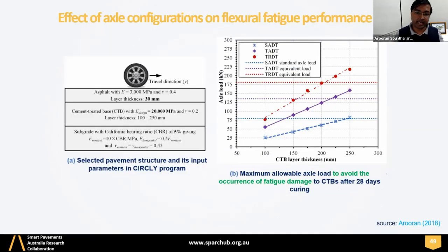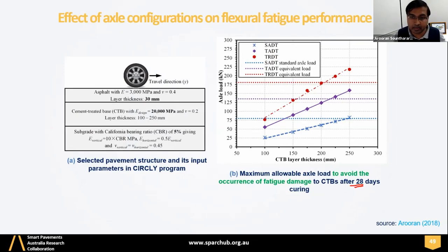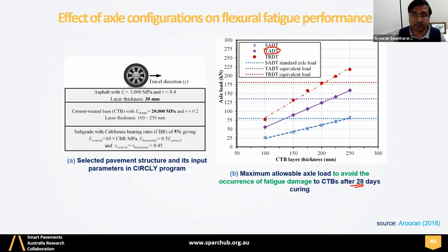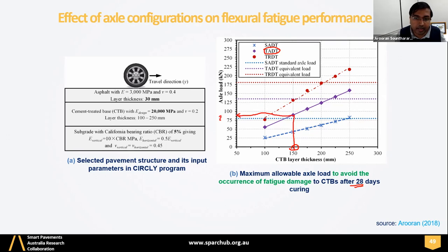Then using the fatigue curves here, we have identified the maximum loads that can be applied on this pavement after 28-day curing. So I will not describe the analysis part behind it, but in a simple graphic illustration, what I can tell you is, if you want your pavement to receive TADT, tandem axle dual tire, what would be the maximum load that you can put on this TADT if your CTB layer thickness is 150 millimeter, right? And then you have TADT here. If I draw the line here, it would be somewhere like, I would say 80 kilonewton, right?